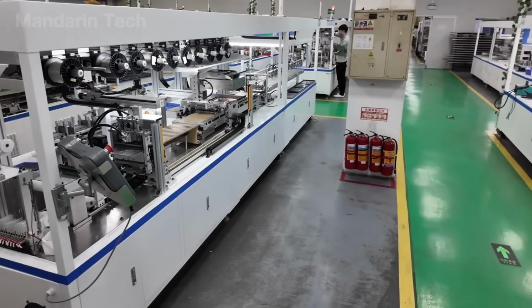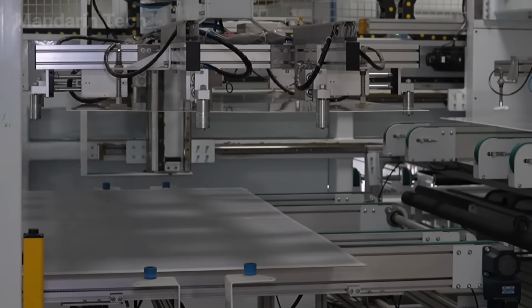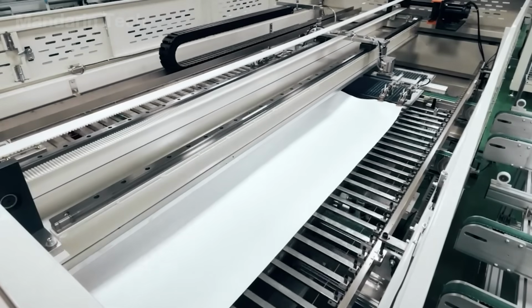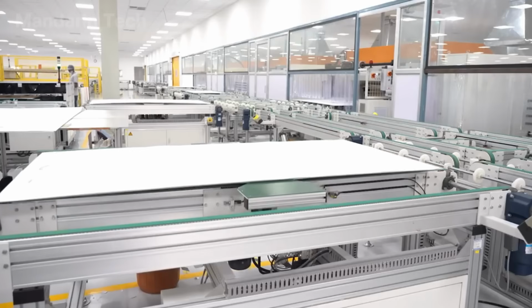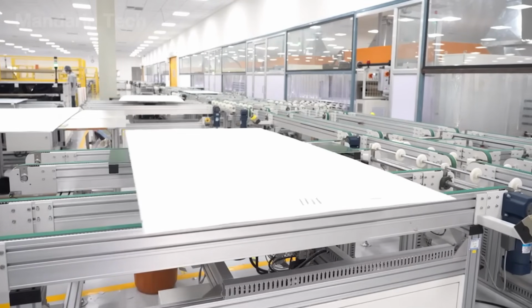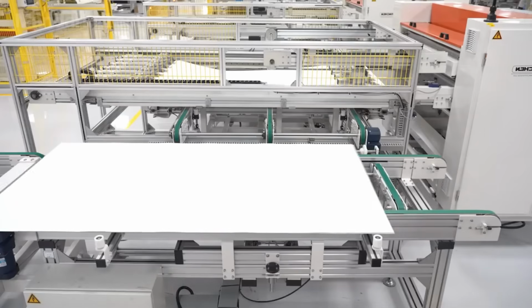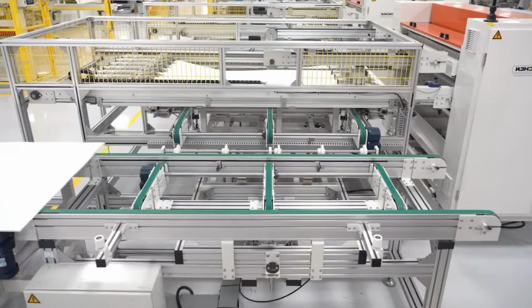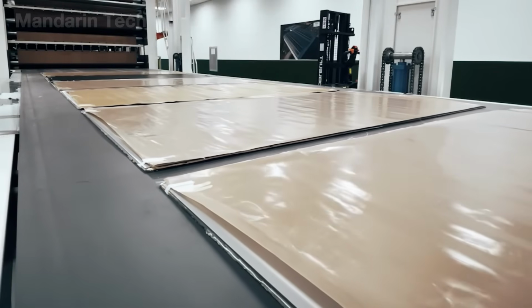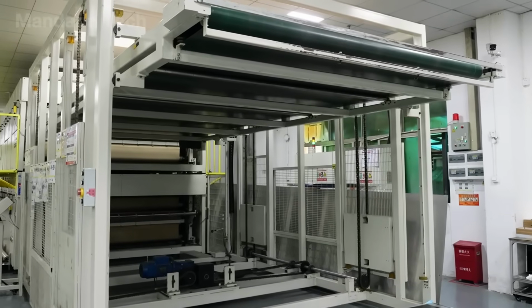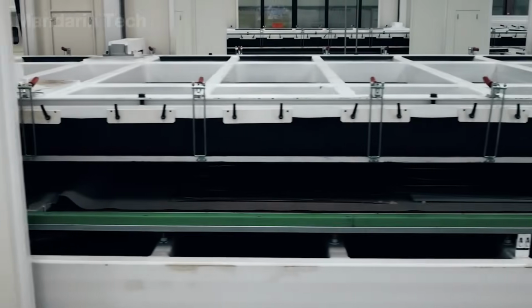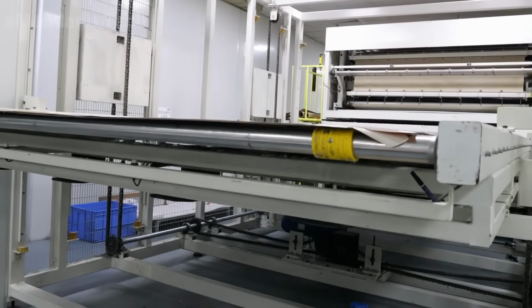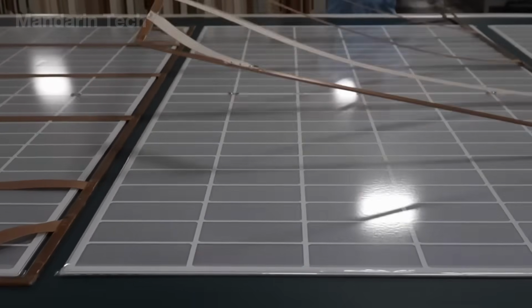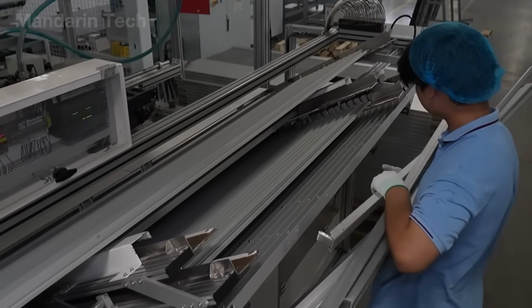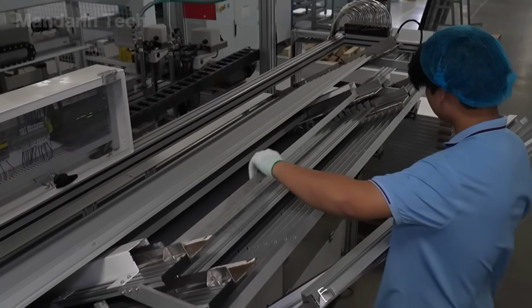The factory falls silent, with only the steady hiss of vacuum pumps echoing through the room. This is the moment when all materials fuse into one, the true heart of the solar panel. Automated robots carefully place each layer: tempered glass, EVA film, photovoltaic cells, protective sheet, and polymer base, precisely aligned to the millimeter. The entire structure is then vacuum laminated at 150 degrees, where ultra-low pressure removes air bubbles and impurities. Under heat and pressure, the layers melt and bond into a single crystal-clear module built to endure 25 years beneath the blazing desert sun. After passing inspection, the panels move to the framing area, where their final form takes shape.